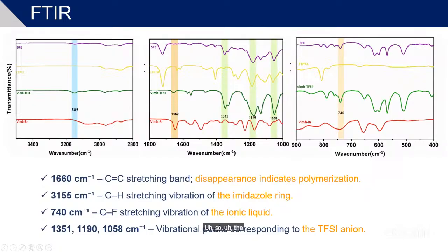The carbon-carbon stretching frequency band at 1660 centimeter inverse, here 1660 centimeter inverse, disappears in the solid polymer electrolyte. That indicates the successful polymerization happened, and the carbon-hydrogen stretching vibration at 3155 centimeter inverse is for the imidazole ring. Then 740 centimeter inverse is the CF stretching vibration in the ionic liquids. And this is another vibration peak, which is for the TFSI anion.